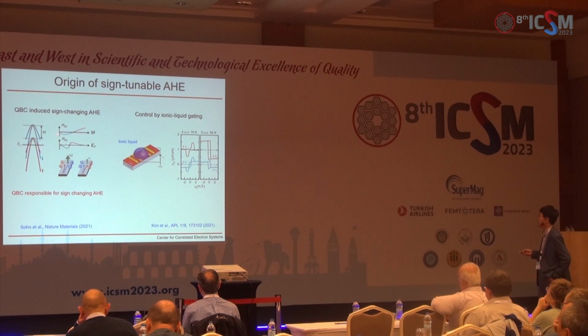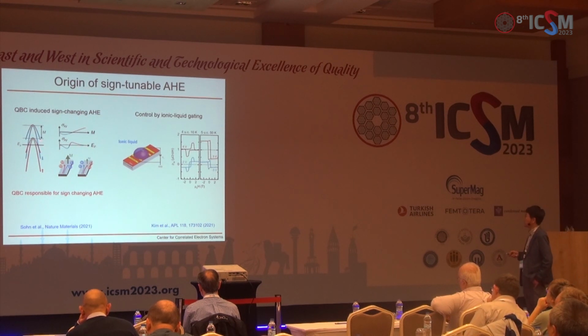As a function of n, as symmetrically shown here, it changes sign. Also, as a function of the Fermi level, up and down, it changes the anomalous Hall conductivity drastically. That means we can actually control the anomalous Hall conductivity by moving the Fermi level up and down. That's exactly what we did.